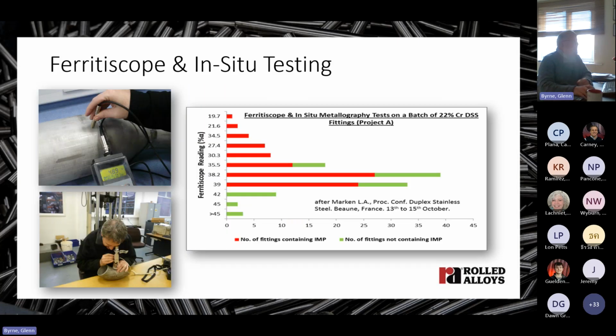So moving on from this, as well as cast and batch testing that we've talked about, microstructure, corrosion and impact testing, it's possible to check individual parts. Intermetallic particles are non-magnetic and they form and grow in the ferrite phase, and this reduces the ferrite content and ferromagnetic strength of the steel. So by using a calibrated device that measures the magnetic pull of the steel, this is called a ferritoscope that you see being used here, it's possible to detect parts with lower magnetic strength, and this is an indication that those parts could well be sensitized.